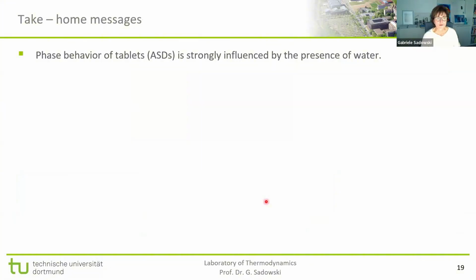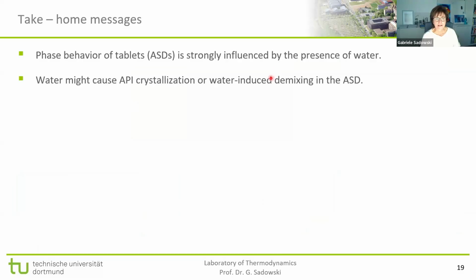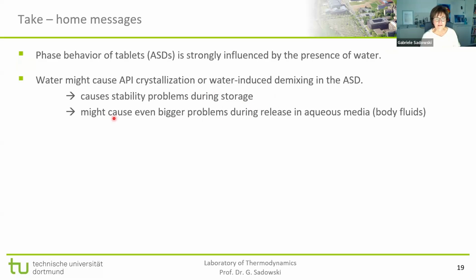And this brings me to the take-home messages. What I've shown you is that water really is the enemy of ASDs. It might cause API crystallization and/or water-induced demixing in the ASDs, and this obviously causes problems during storage, but unfortunately not only during storage where we could avoid having water, but it even causes bigger problems during release because we cannot avoid the presence of water during release in body fluids, obviously.